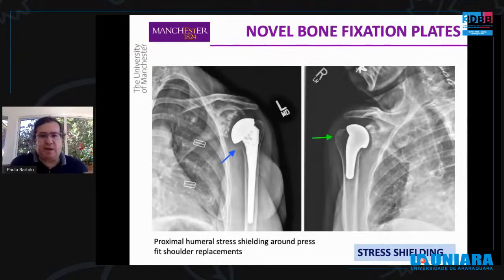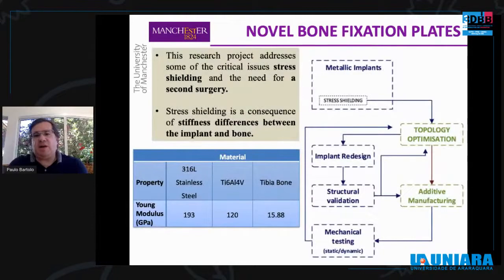And the first problem that we target was the stress shielding problem, and consequently the bone loss issues associated with this stress shielding, which is due to the mechanical mismatch between the mechanical properties of the implant and the mechanical properties of bone. We solved this problem using topology optimization to redesign the shape of commercial available plates, printed using additive manufacturing technologies, in this case using titanium 64. Basically, topology optimization is used to remove materials from areas where the material is no longer needed and decrease the equivalent stiffness of the plates.